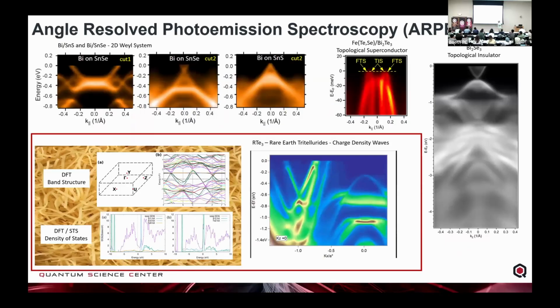So in essence, what we're doing is we're looking at the band structure. We're directly measuring the electronic band structure of the material. With our analyzers, we're down to millivolt resolution. And so we can get a lot of exquisite details in how the electrons behave inside these materials, down with millivolt resolution, and we can go very deep down into the bands. But now to get back to your question about the comparison between what we can see in ARPES and what we can see in STM.